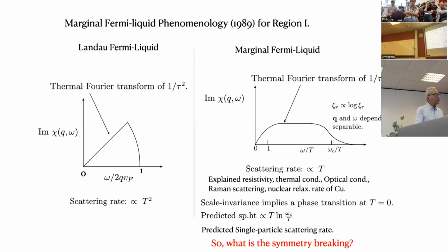And very importantly, I got confidence in this idea only when the single particle scattering rate was measured, and that happened about 10 years after the proposal, when angle resolved photoemission was developed as a quantitative technique. But we are saying there's a critical point at T going to 0. So the question is, is there a symmetry breaking? Is there a critical point, a critical phase, etc.? And we have to answer the question, what is the symmetry breaking, such that the fluctuations of that phase lead to this spectrum.